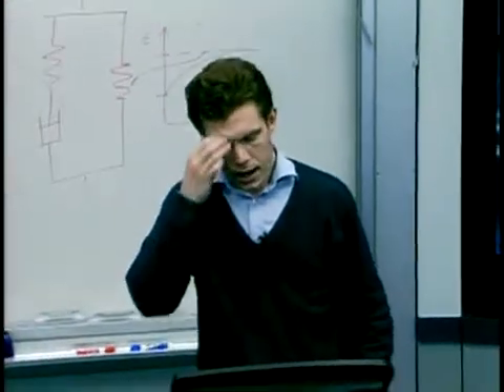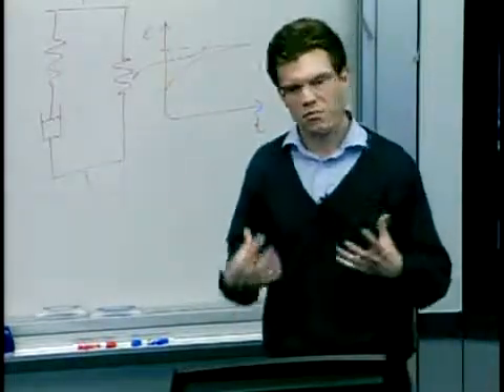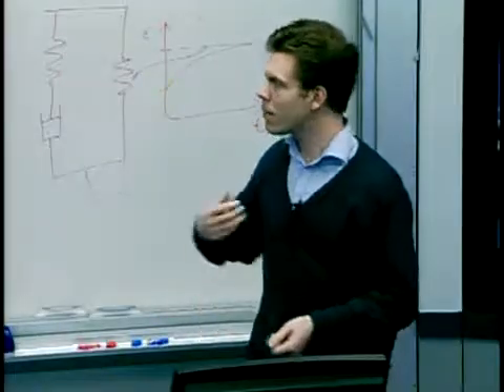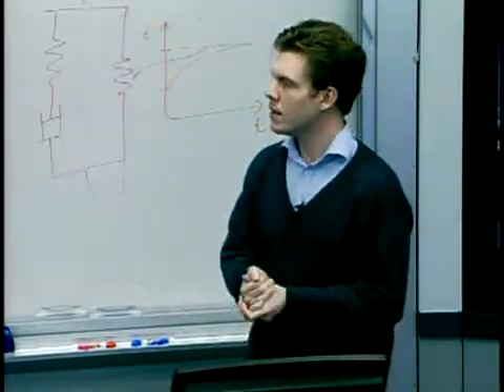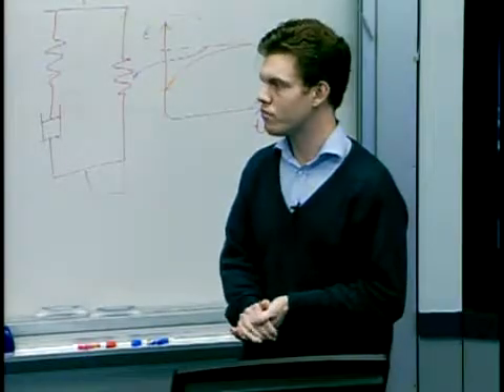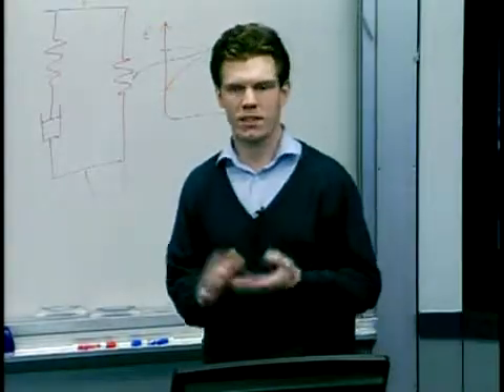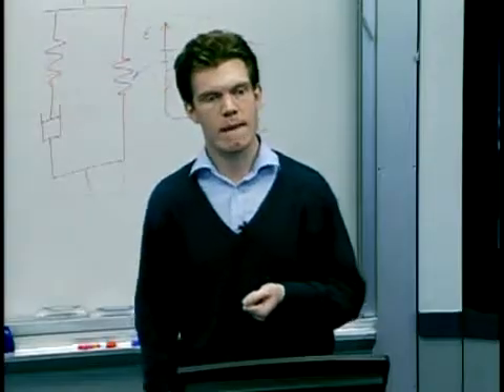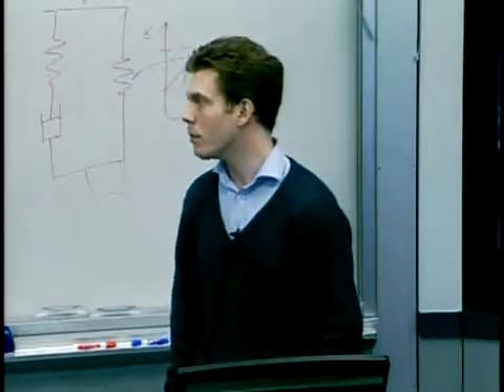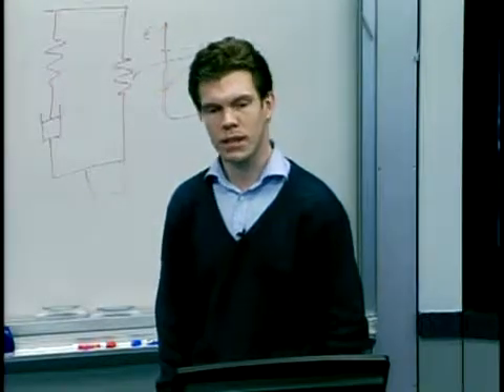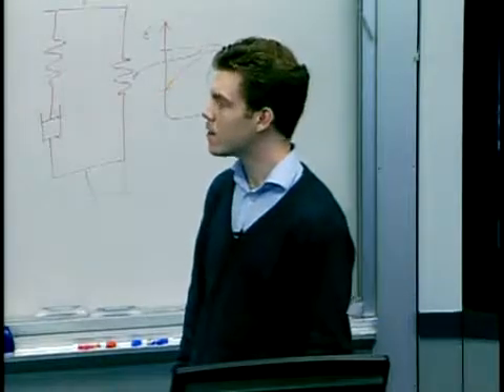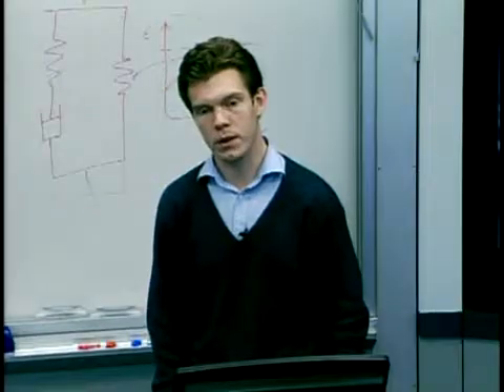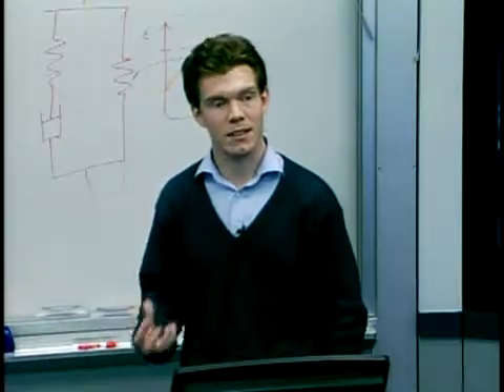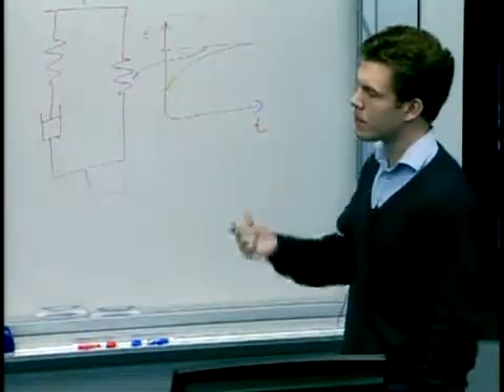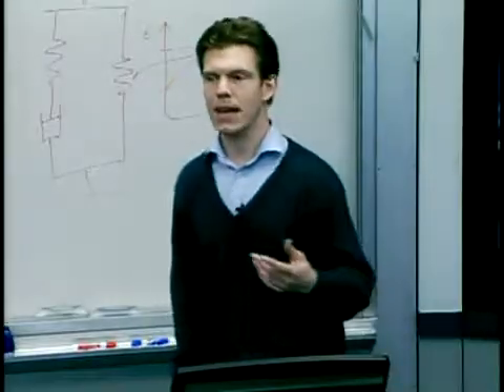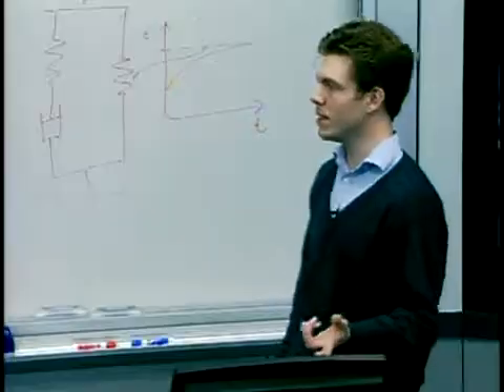So, of course, now that we've got this characterization idea, we can apply that to different materials, and we did it with this cyclic olefin polymer, Zeonor, which is a thermoplastic. This one softens around 135 degrees C. It has quite a few advantages over PMMA. Although it's more expensive, it doesn't absorb water as readily, which is pretty relevant to microfluidic devices. It transmits light to shorter wavelengths, which is relevant when you're exciting fluorescent tags inside the chip with UV light. And so it's useful to be able to characterize these new materials as they come along, and when you don't necessarily have an unlimited supply of the material.